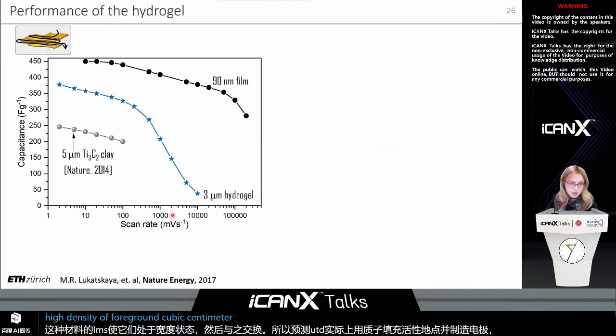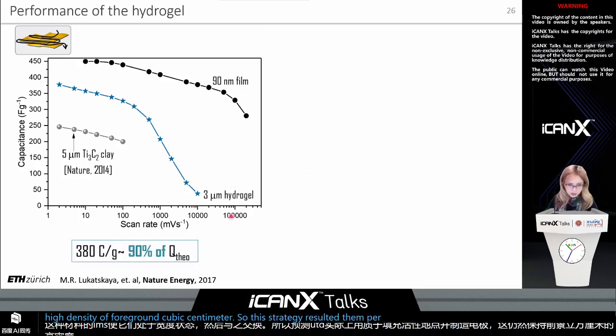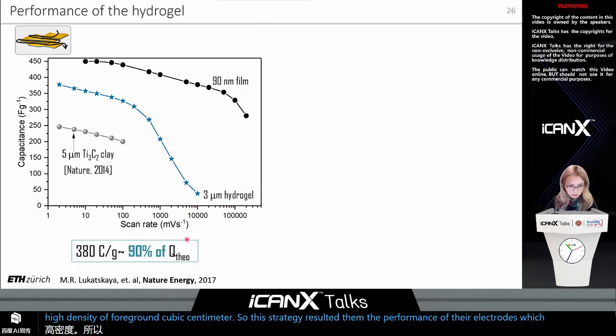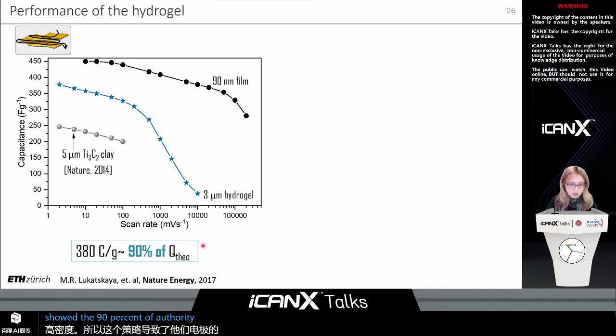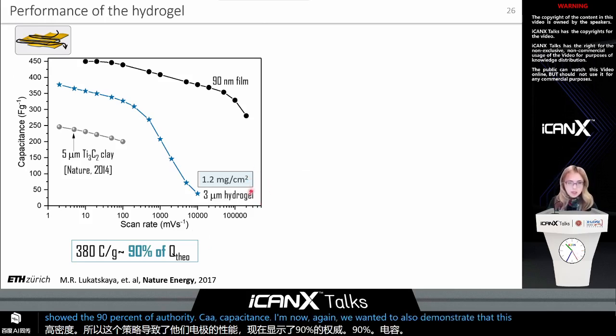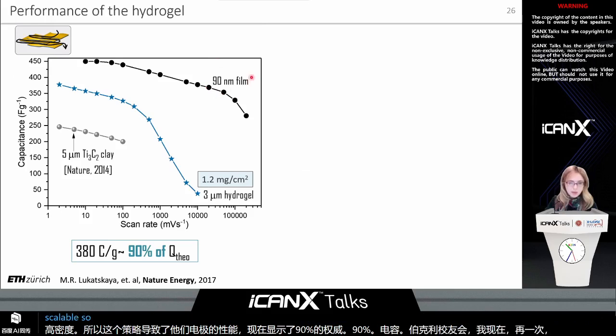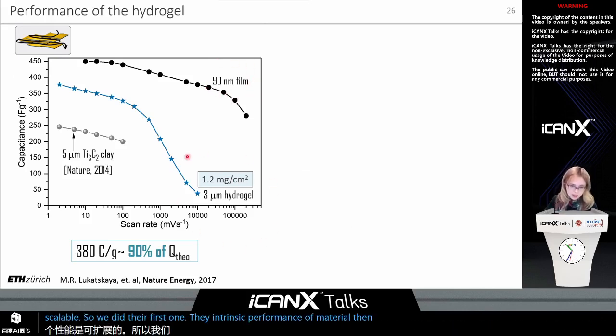So this strategy resulted in the performance of the electrodes, which right now show 90% of theoretical capacitance. Again, we wanted to also demonstrate that this performance can be scalable. So we did the first one, the intrinsic performance of the material, then the electrode at its rather thin state.